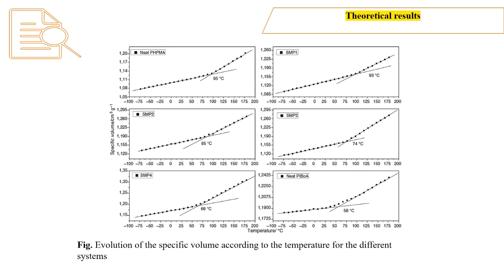Then, to predict the glass transition temperature of a polymer system in molecular dynamics simulation, we often use the theoretical approach called the dilatometric method. It consists in following the change in the density of the system as a function of the temperature variation. By plotting the values of the inverse of the density, or specific volume, for each temperature, it is possible to define an estimate of the Tg value.